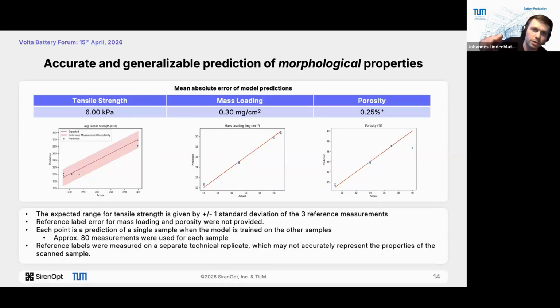This is why, on the left side for the average tensile strength, you see this red bar across the picture. But for the mass loading and the porosity, as you can see, we already achieved quite good precision, with mean absolute errors of 0.3 milligram per squared centimeter and 0.25% of porosity. For the porosity especially, it's very difficult to measure exactly. So at the moment, the first models performed quite good.